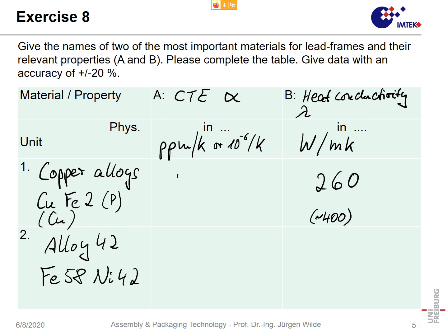The CTE here is very similar to the CTE of pure copper. Here you could say it is roughly 16 ppm per Kelvin. Please note the CTE is mostly determined by the crystal structure, and the crystal structure is not affected by this 2% of iron. Okay, so it's 16 ppm per Kelvin, or some also say 16 micrometer per meter and Kelvin. That means if it's a meter bar and you increase temperature by 1 degree, it will expand by 16 micrometer.